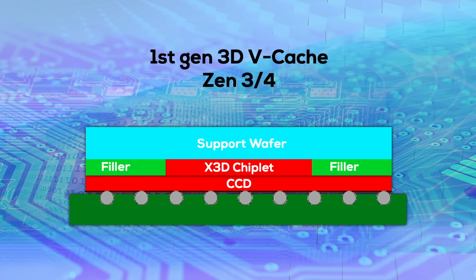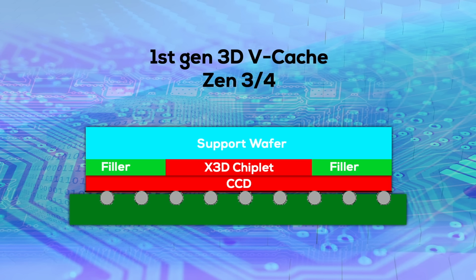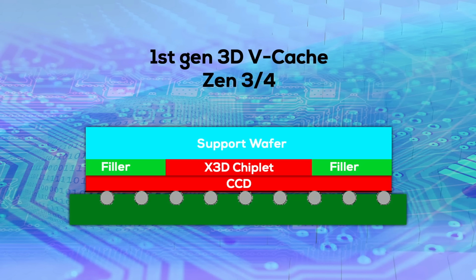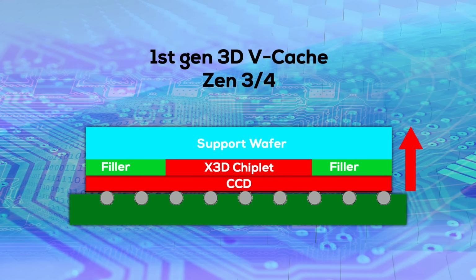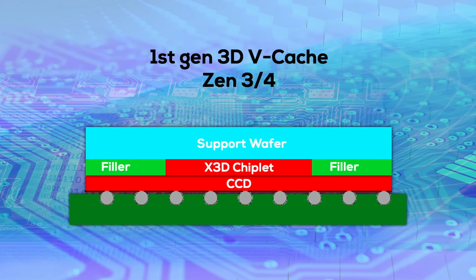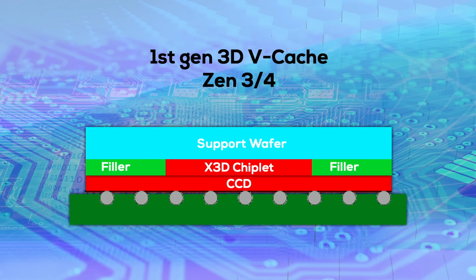This layout also explains the thermal issues of Zen 3 and Zen 4 X3D CPUs. The problem isn't the amount of silicon that sits in between the CCD and the heat spreader. Both variants are the same height. It's also not the 3D V-cache that does produce some heat, because it only covers the cache areas of the CCD. The real reason is all the bonding layers.